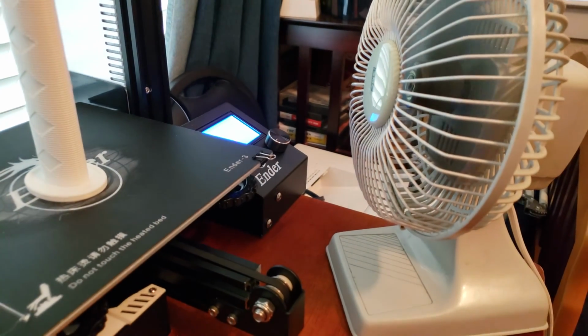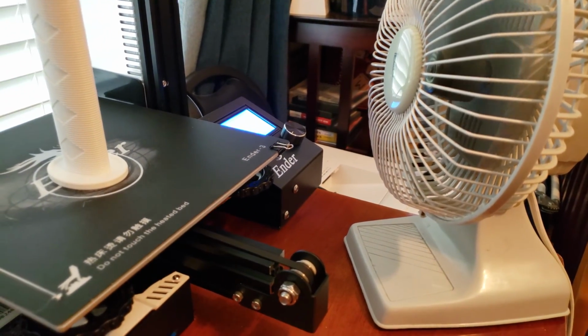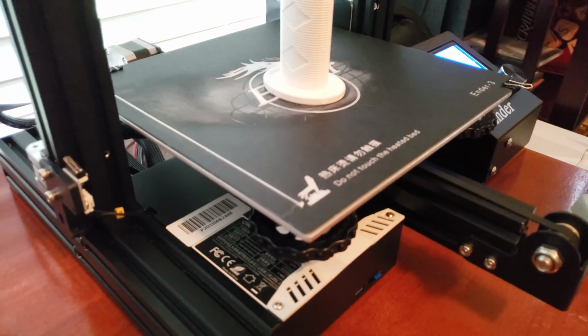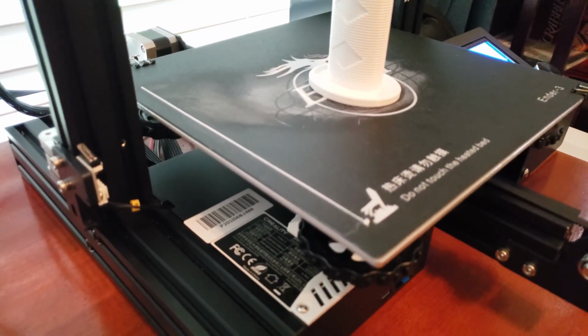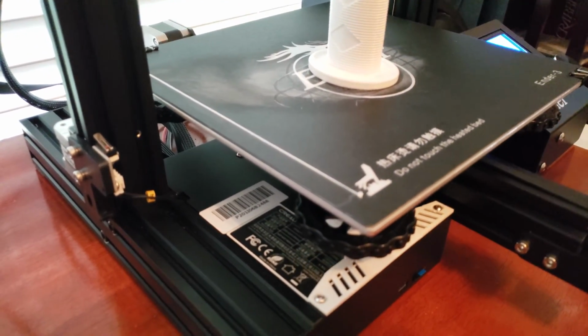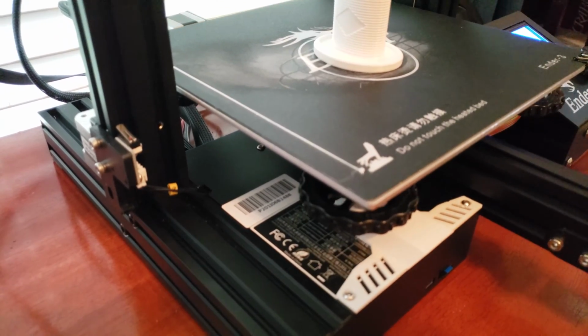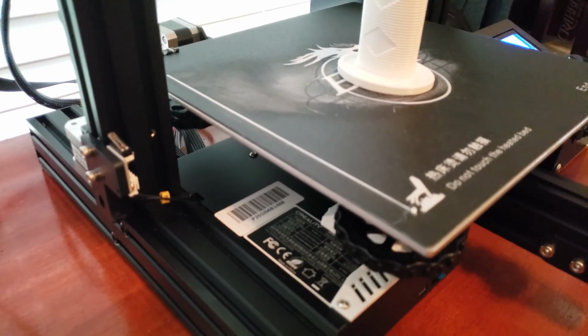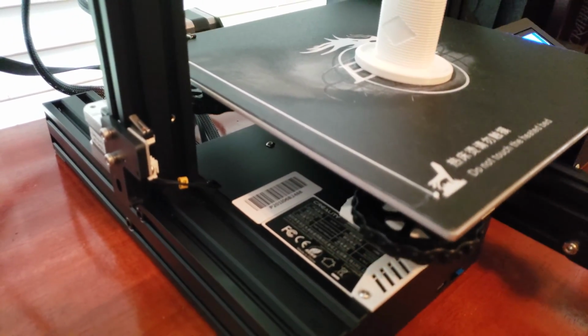I also added a fan, like I said, to help with cooling the plastic, which definitely helped. And one of the most important things is that the printing bed is set at 48 degrees Celsius, or at least not 60 or 50. 50 was still too hot for me. So I believe that'll help.